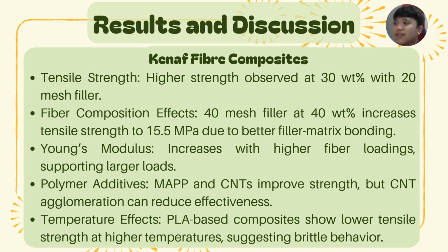Kenaf fiber composites. Tensile strength: highest strength observed at 30 wt% with 20 mesh filler. Fiber composite effects: 40 mesh filler at 40 wt% increases tensile strength to 15.5 megapascal due to better filler-matrix bonding. Young's modulus increases with higher fiber loading, supporting larger loads. Polymer additives: MAPP and CNTs improve strength, but CNT agglomeration can reduce effectiveness. Temperature effects: PLA-based composites show lower tensile strength at higher temperatures, suggesting brittle behavior.